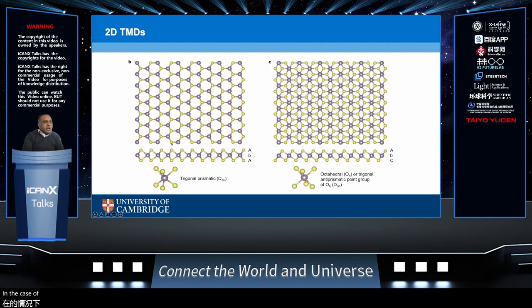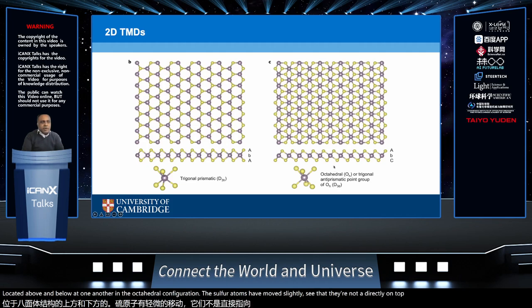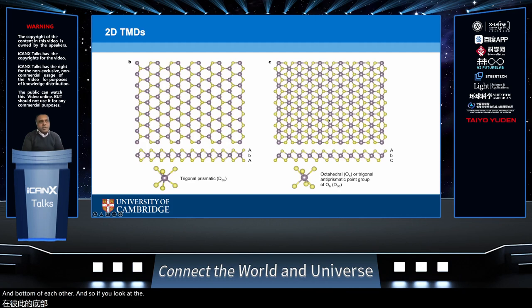In the case of the hexagonal phase, the 2H phase, the sulfur atoms are directly located above and below one another. In the octahedral configuration, the sulfur atoms have moved slightly, so you see that they're not directly on top and bottom of each other. If you look at the octahedral structure from the top view, we can see that there's a sulfur atom in the middle of the hexagonal structure. This very slight change in the structure leads to dramatic changes in the electronic properties. As I said, this is a nearly two eV band gap semiconductor, and this is essentially a metal. And again, I'll be talking about the metal phase.